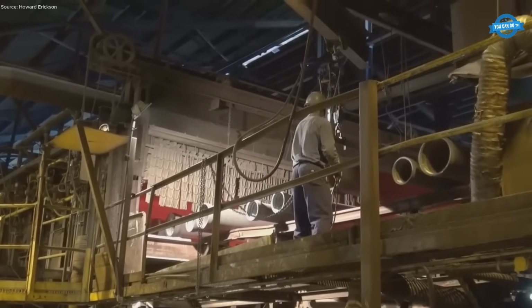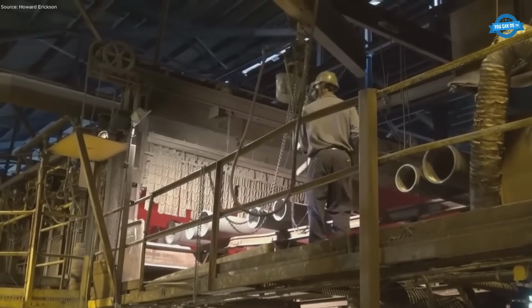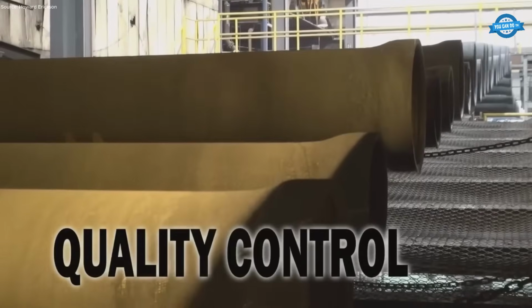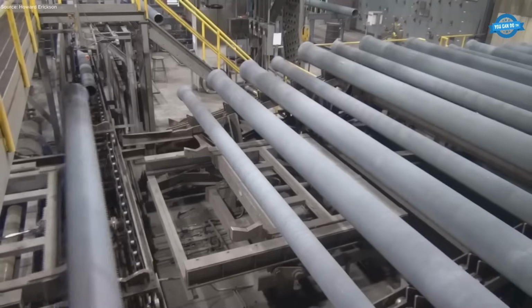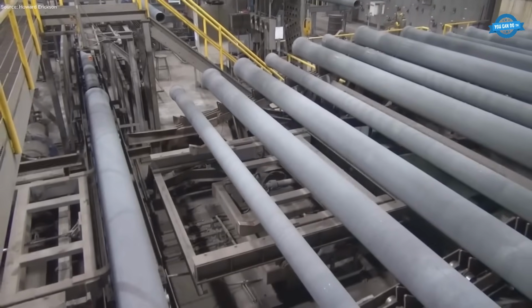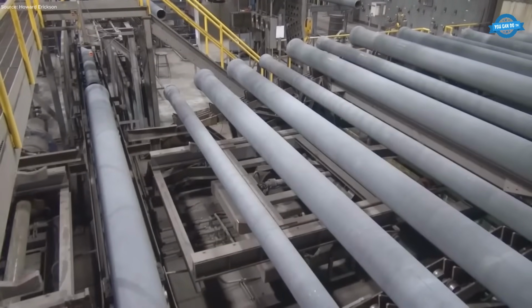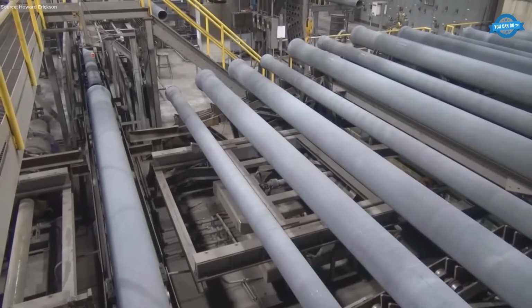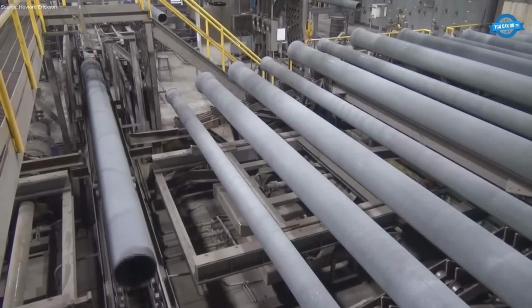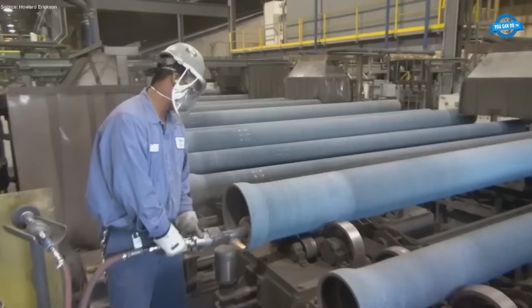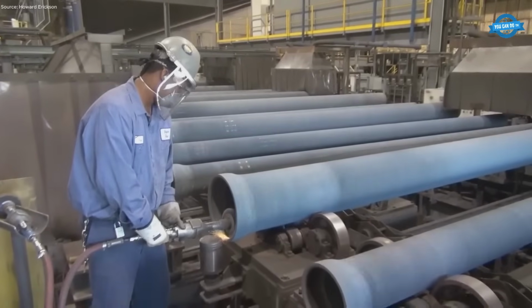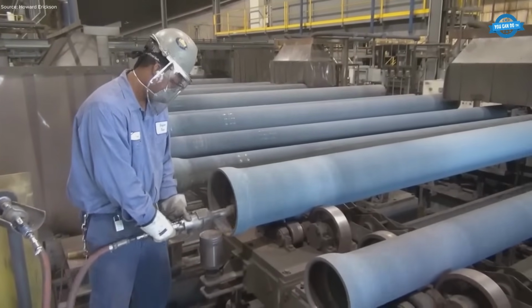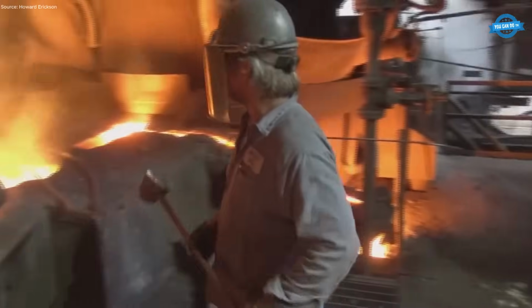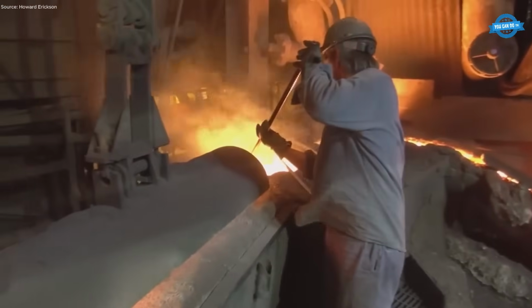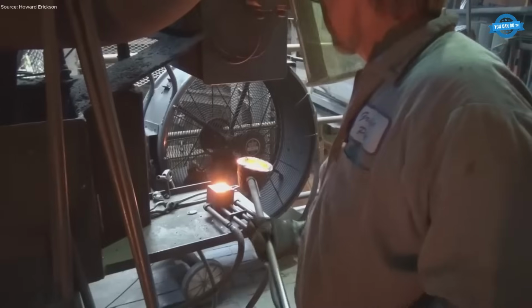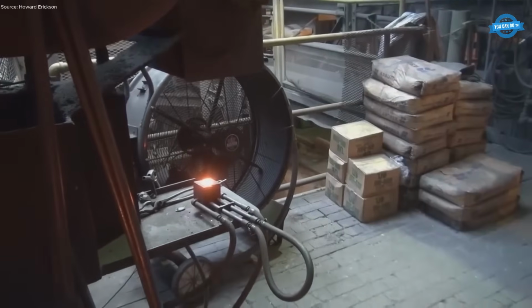Hydrostatic testing is conducted on every pipe to verify its structural integrity and leak tightness. Pipes are filled with water and pressurized to levels above their intended service pressure, held for a specified duration, while inspectors monitor for leaks, bulges, or deformation. Test data is recorded and tied to each pipe's identification number for traceability. Following testing, a final inspection is carried out to confirm all dimensional specifications, surface finish quality, coating integrity, and lining condition. Any non-conforming pipes are either reprocessed or rejected.